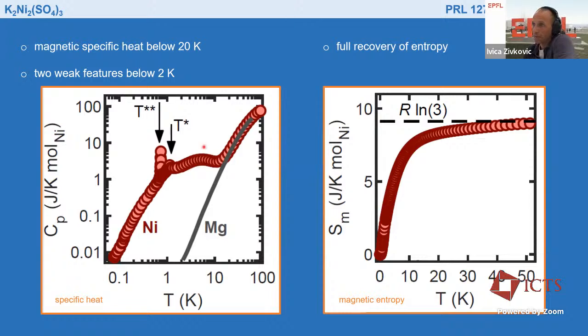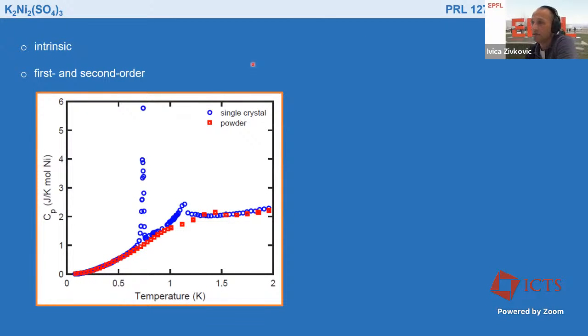On top of this broad feature, there are these two small features designated with T star and T double star. And so one could ask whether this is impurity or something intrinsic. And we believe that this is actually intrinsic. So you can see here the comparison of specific heat on a powder and on a single crystal.